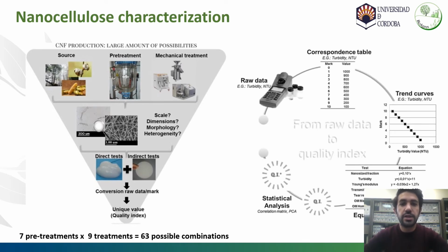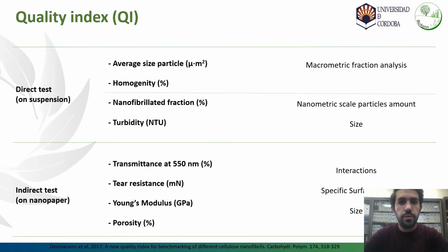In this case, first, it is necessary to define the quality requirement that will define the quality index and what analysis will be performed to reflect this quality requirement. Secondly, it is necessary to determine the scope of application for the cellulose nanofibers obtained. In this work, we are going to use the quality index proposed by the Desmaisons et al. and will try to explain it briefly. For this analysis, 8 parameters were established in order to represent all the aspects of the nanofibers. Half of the tests were performed on the suspension, which are called direct tests, and the other half were performed after the transformation of the suspension into a nanopaper, which we call indirect tests.